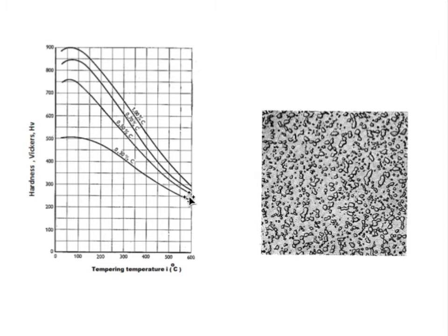But this is not the spheroidite. If you really should continue to do this at maybe 650 and 700 degrees and go on for about 20 hours, then we will get to the good spheroidite, and we can assume that the curve still continues to go down somewhat. And then, before we get this type of structure, this is a spheroidite structure. And what we see here is the particles of cementite. They are rather large and they are well rounded. And the matrix here around them is ferrite with low carbon content. Therefore, there is a very soft matrix with these hard round particles.